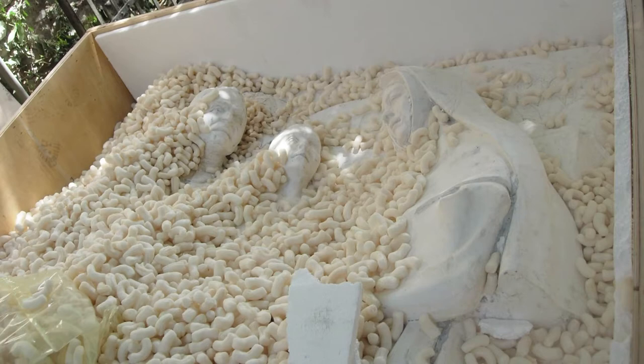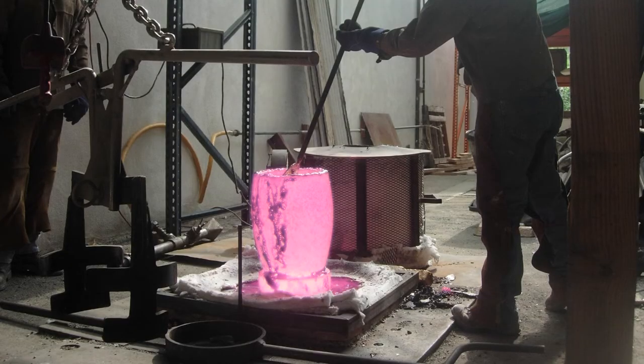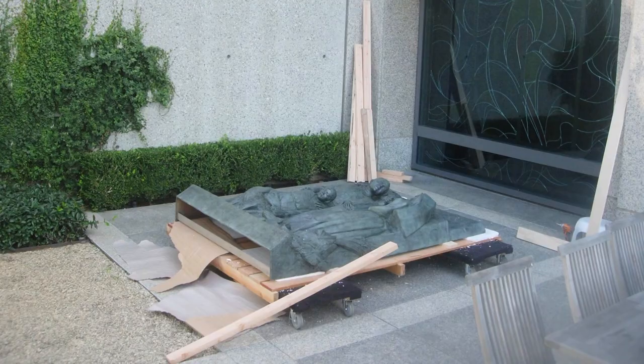From the design phase up until making that waste mold, all of that was completed here on campus. Then once the plaster cast was completed, we shipped it out to a foundry in Italy where a subsequent rubber mold was made, a wax copy was made from the rubber mold, and more work was done on the wax version. The wax is used to make a bronze cast using an old technique called the lost wax method, and ultimately the bronze was touched up in some areas, a patina was given, then shipped and installed.